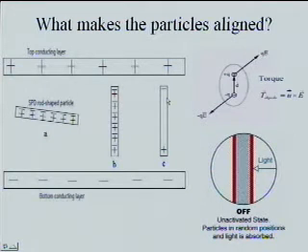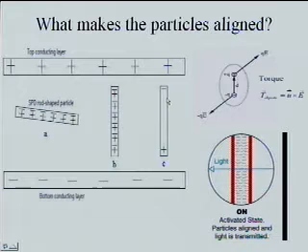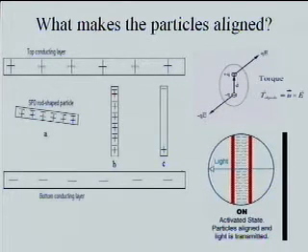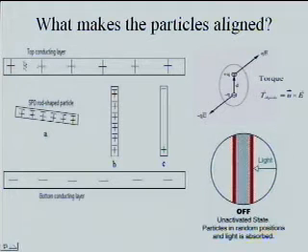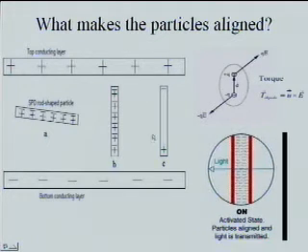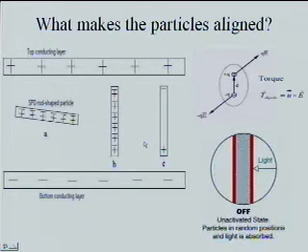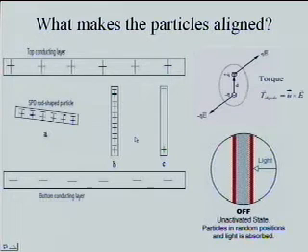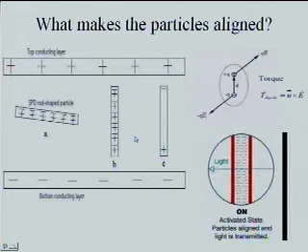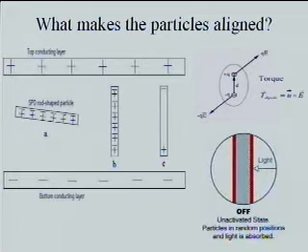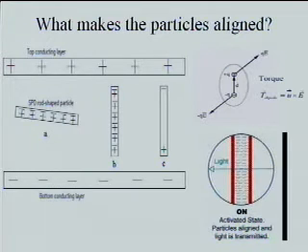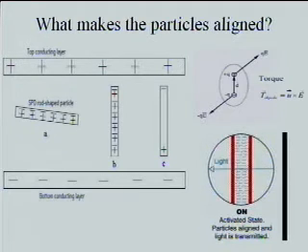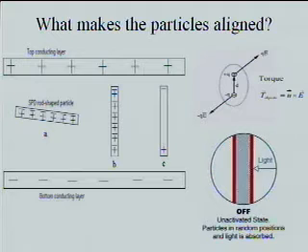Mechanically, what we'll see is that it was dark. We apply DC voltage, and it stays dark. Nothing happens because particles will accumulate on the top and bottom and cover the whole surface. So to avoid that, of course, AC voltage is used, or there is another technique that deals with encapsulating particles inside very small immobile droplets, called SPD film. I'm going to talk about that on the next slide, but I just wanted to mention some physics here.